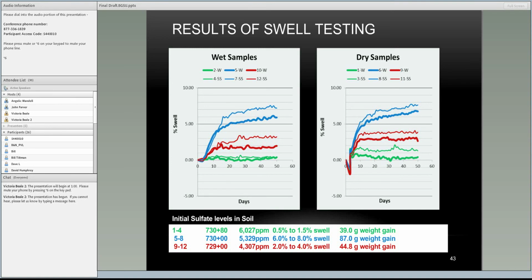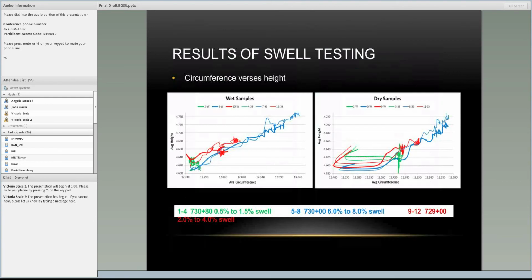Here's just another way of looking at the samples. This is looking at the average circumference measurements on the bottom versus the average height. And what you can see is 730, the samples that swelled the most, pretty much continued swelling throughout the whole 56 days. Whereas 729, you can see it kind of stopped growing midway through the experiment. And then 730 plus 80, which had a small percentage of swell, swelled a little bit in the beginning of the experiment and then pretty much stopped. And the squiggles back and forth are just a result of the slight differences in the measurements from day to day once the swelling had stopped.